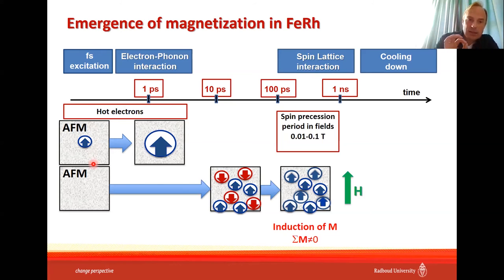And we can launch two kinds of processes. Those ferromagnetic nuclei which were already present in the medium before the excitation will expand. This expansion is fast, on a time scale of 1 picosecond, and as a result of it we can see terahertz emission from a single pulse in the medium. There is also another process. You pump the antiferromagnetic state, purely antiferromagnetic state, and you generate many nuclei. The nuclei will have random magnetizations, and they will start to align their magnetizations in the applied magnetic field on a time scale of 100 picoseconds.